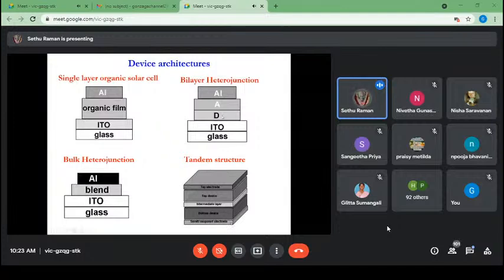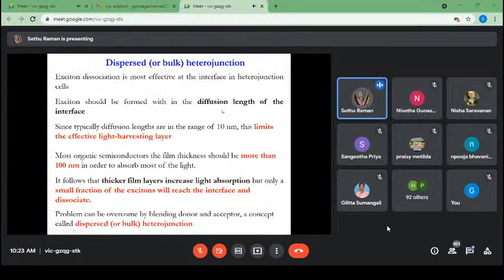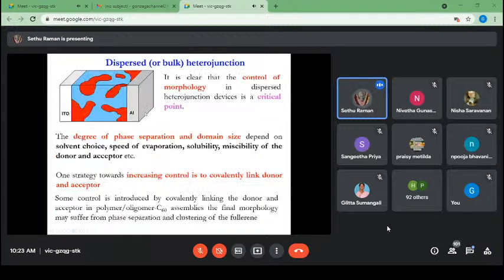In traditional heterojunctions, the exciton is generated and diffuses towards the interface. Generally, dissociation happens at the interface. If the layer is more than 100 nanometers thick, the number of excitons reaching the interface is very small, so it will reduce the power conversion efficiency. That's the reason people are now going for the concept of a dispersed or bulk heterojunction. This is a bulk or dispersed heterojunction structure.